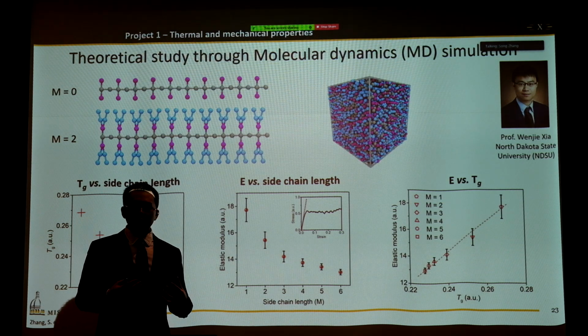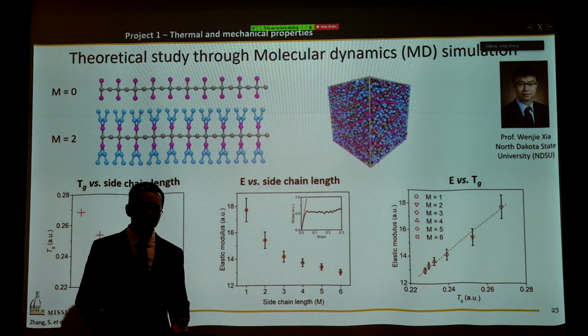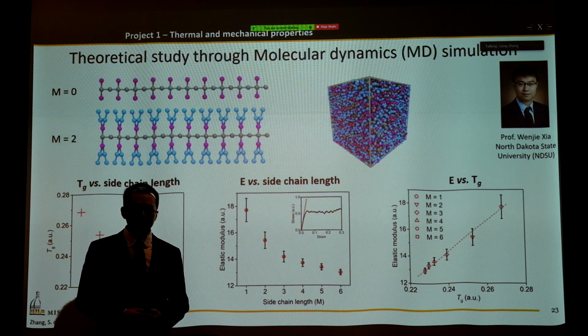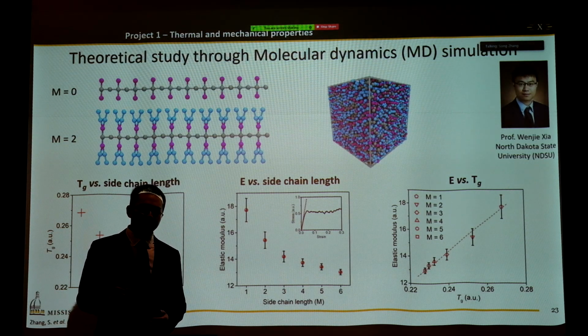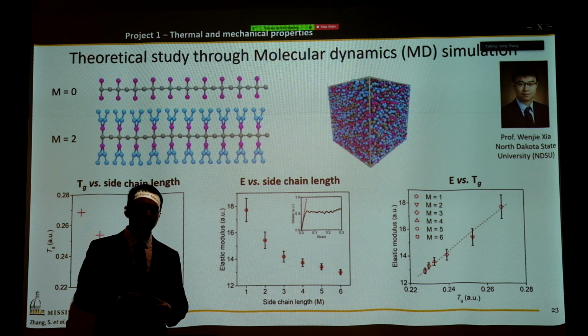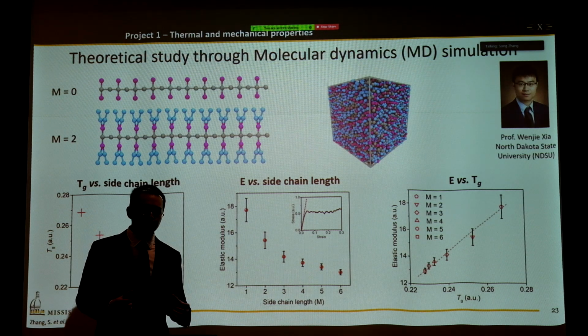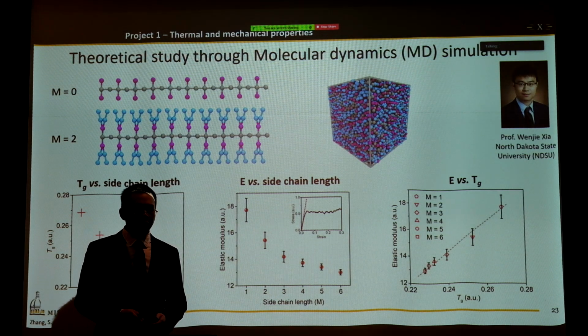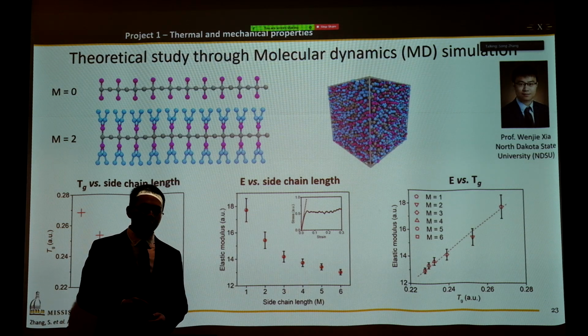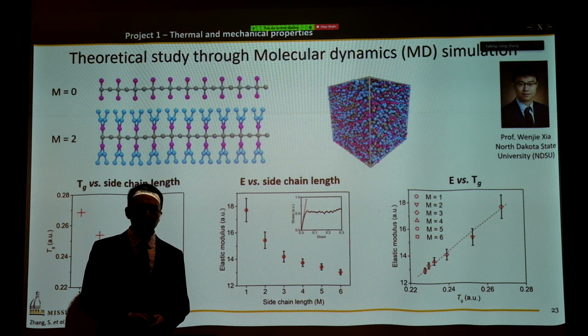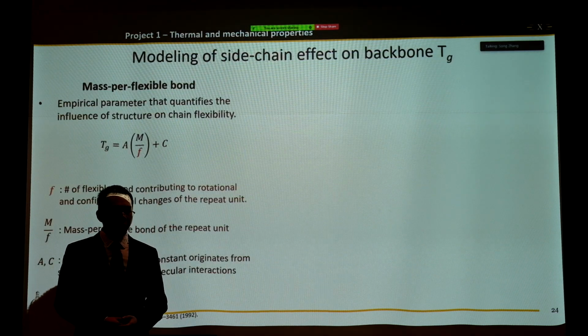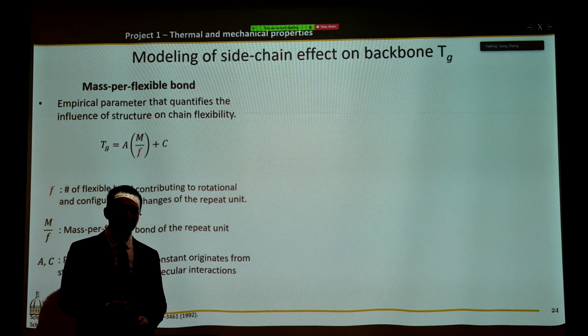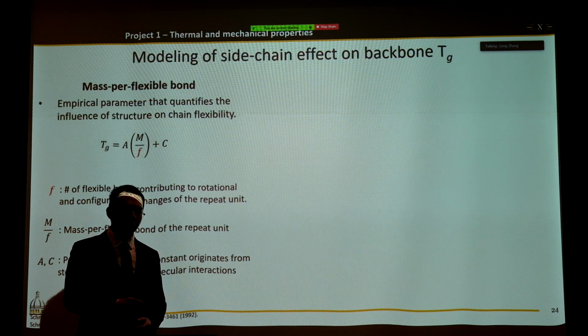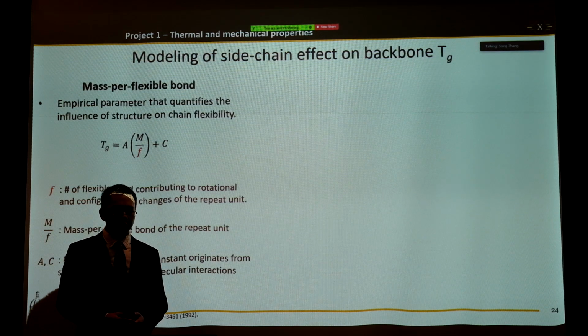But still, if we want to use this model to predict the glass transition, it seems to be pretty hard. So how do we do it? We consider that the side chain fraction is affecting the backbone dynamics, and the Tg of the backbone dynamics will be represented by the flexibility of the repeating unit. Now we need to understand how the side chain affects the flexibility of this repeating unit. With that in mind, we went into the literature and found a model called the mass per flexible bond model, which was previously applied to polycarbonate material.